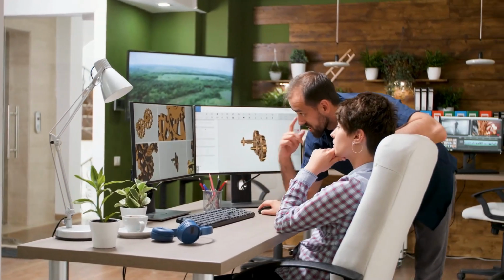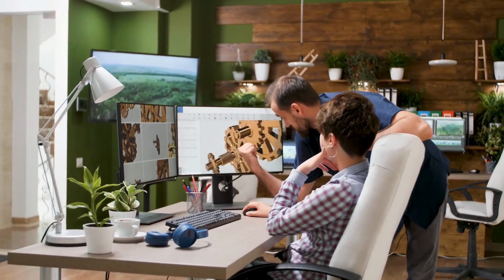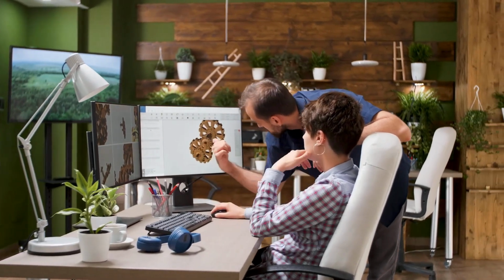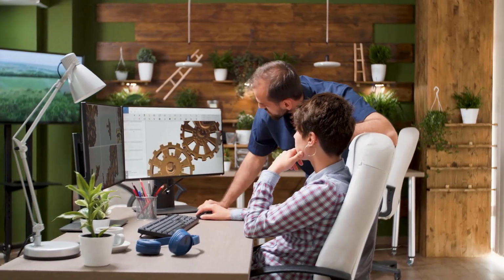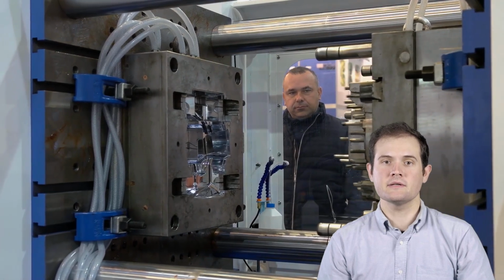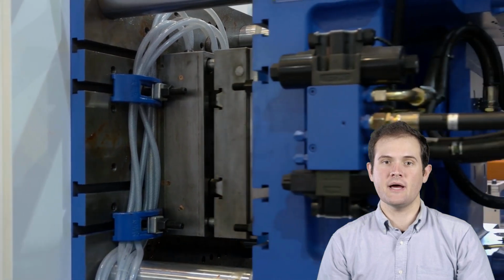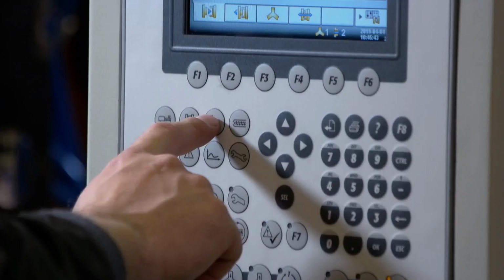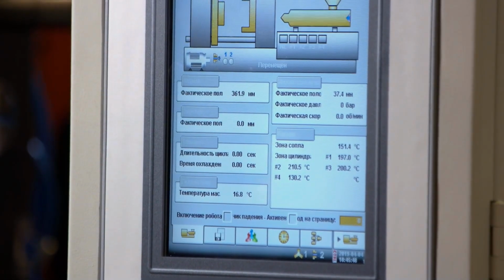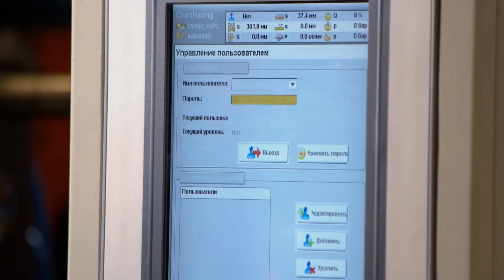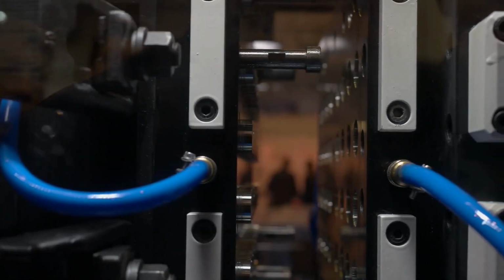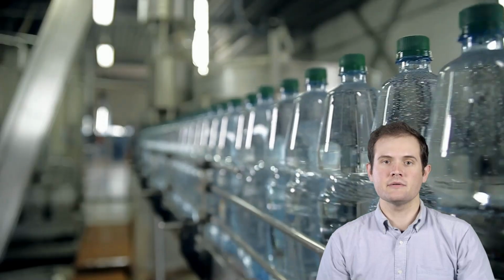Low injection speed allows for more controlled and uniform flow, reducing differential shrinkage. Minimizes shear-induced stress, lowering the chances of warpage. Can lead to premature cooling in thin sections, resulting in flow hesitation and uneven part thickness. Use a moderate injection speed to balance shear stress and flow uniformity. Optimize the speed profile. Start with a higher speed to fill the mold quickly, then slow down near the end to reduce stress buildup. Consider material behavior. Some polymers require slower speeds to avoid orientation-induced warpage.